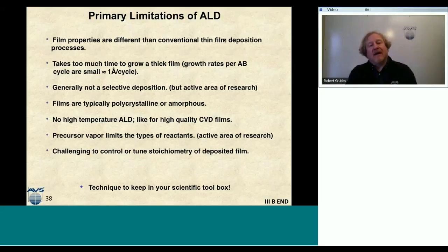And also the last limitation is that it's pretty challenging to control or tune the stoichiometry of the film. We're really only limited by what happens on the surface to determine what the stoichiometry is, whereas in CVD, we can bring in 10 times as much ammonia versus silane to make silicon nitride, or we can tune the flow. We really can't tune the flow in ALD in order to tune the stoichiometry. So you kind of get what you have with the ALD deposited film, because that chemistry only happens on the surface. With all those primary limitations said, this is a very important technique to keep in your scientific toolbox.